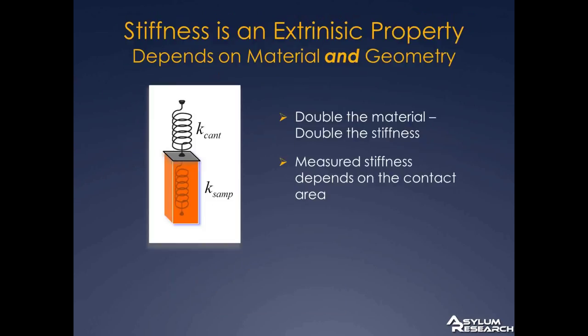So stiffness, as I said, is an extrinsic property. It depends on the material and the geometry. The idea is if you double the material, it doubles the stiffness. What that means in the case of nanomechanical measurements is that real AFM tips have a physical shape, and that shape will determine how much contact they make with the sample. So the details of the shape have important consequences for how much of the material is actually touched by the probe. This contact area depends on the shape, the loading force, adhesion, and other factors.